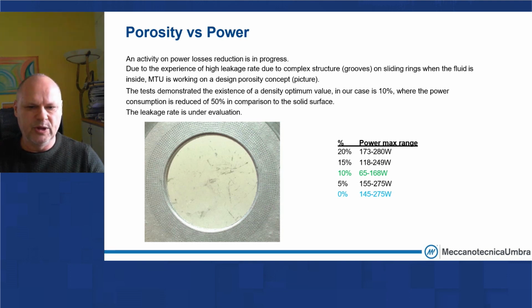We also try to find a solution to reduce the power consumption of this sealing system. One solution for obtaining the result is to design some particular geometry on the face of the mechanical seal. In this case, we apply a pattern of dots, and working on the density of these dots, we define an optimum percentage of dots where the power consumption is used in a range of 65 to 168 watts.